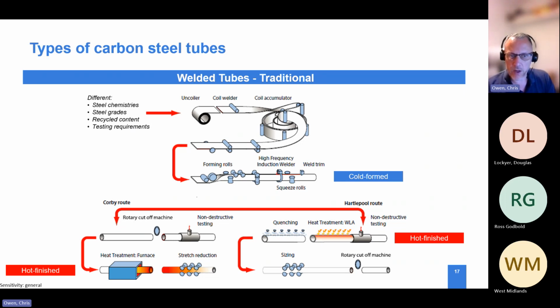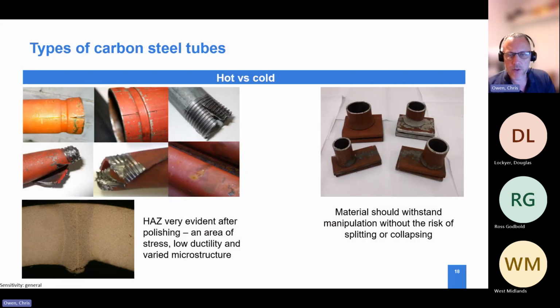What we then do at Tata is we take that cold form tube and we'll put it through either a furnace for full body normalization or weld line annealing, which applies localized heat at that weld seam to remove those stresses and remove what we call the heat affected zone. And the reason why we do that is because the weld seam is an area of weakness. It's an area of stress where the mechanical properties are very different. The heat affected zone is very visible when you take a section of that tube and polish it up. You can clearly see the discoloration.